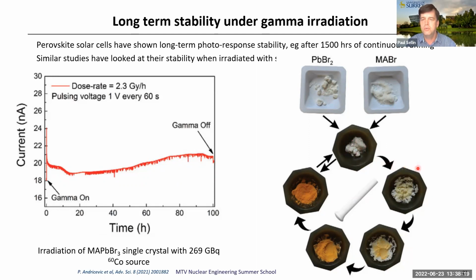And you can see that with each iteration of the stirring, there's a spontaneous room temperature reaction, materials going from white to orange, and finally, with enough agitation, a full synthesis of the orange material, which is MA lead bromide, is produced. Of course, in reality, you can do this in an automated way with a ball mill, and you can show direct chemical synthesis by energetic mechanical mixing.